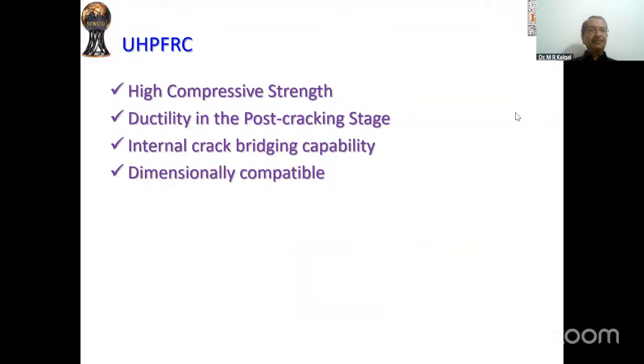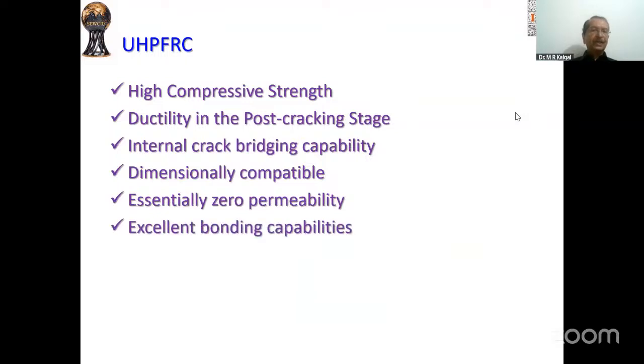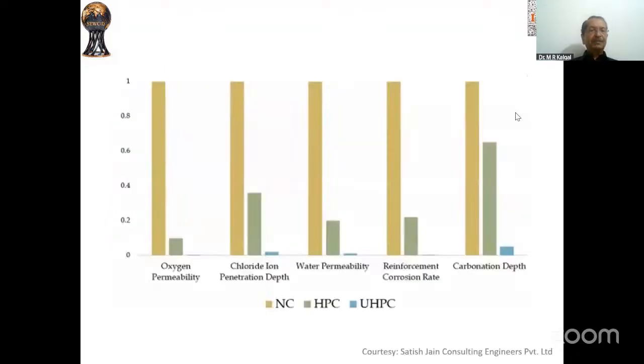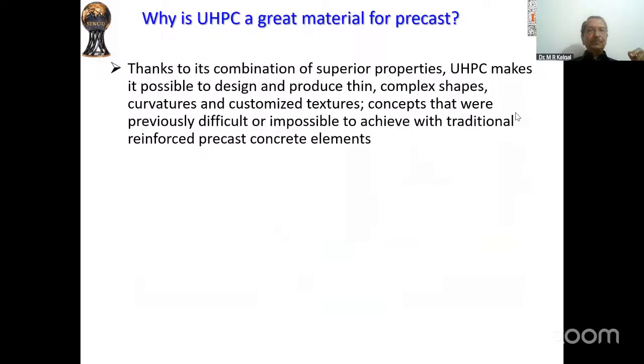It has dimensional compatibility. It has essentially zero permeability and hence long lasting, excellent bonding capacities. This is something which is very unique to UHPC. Abrasion resistance similar to rocks. So if you see the comparison, you will see that the blue one on the right side has the least oxygen permeability, chloride ion penetration, water permeability, reinforcement corrosion rate, and carbonation depth.